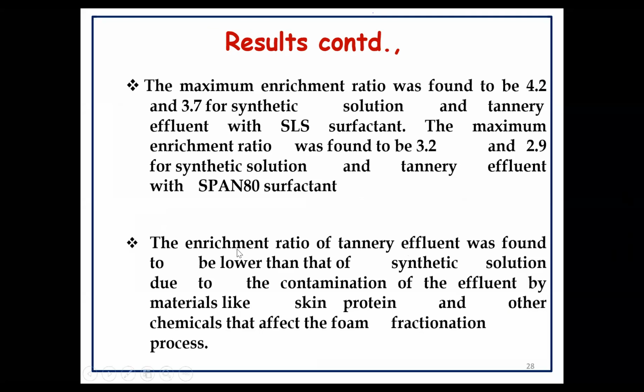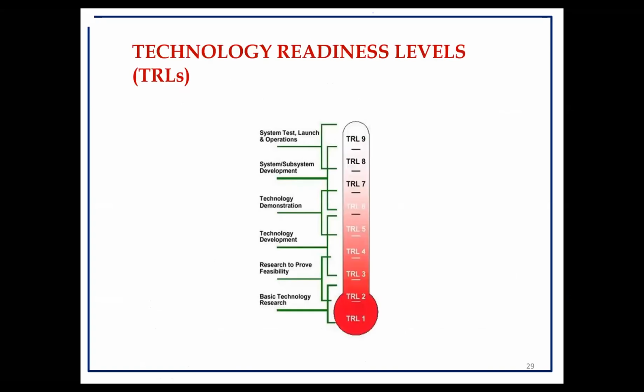So the maximum enrichment ratio was around 3.7 for the tannery effluent. We were able to get only a little lesser efficiency for the tannery effluent because of the contamination of the effluent and interference by the skins and the proteins present in it. So that has to be filtered. Pre-treatment has to be done before going for this foam separation operation. So I close this foam separation operation with this introduction.